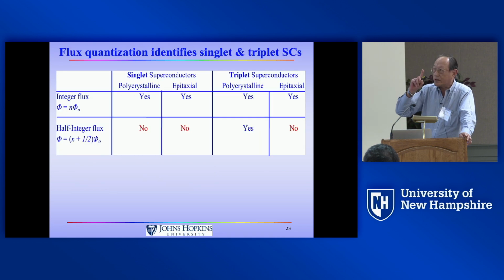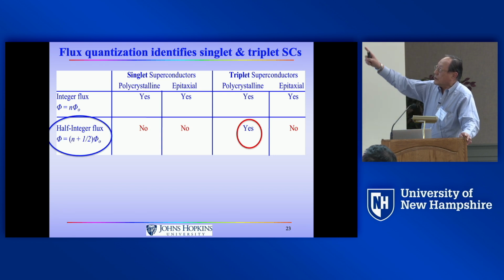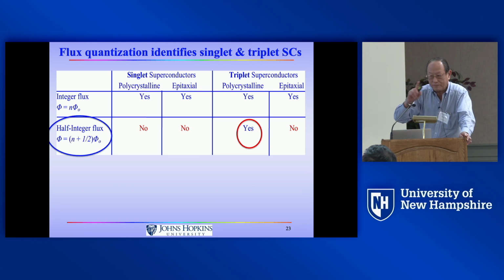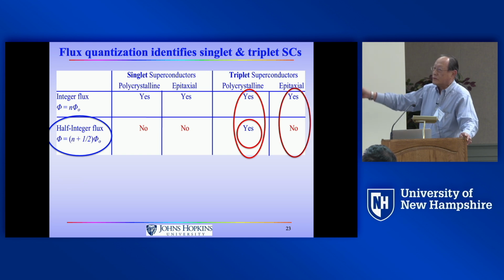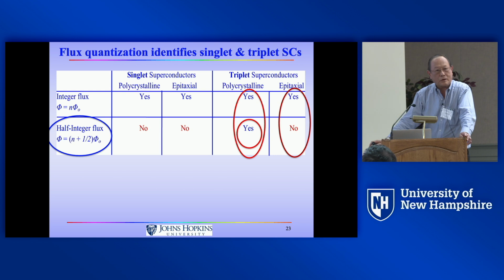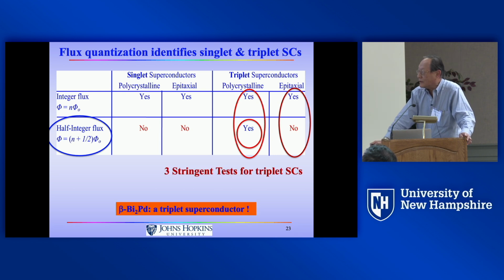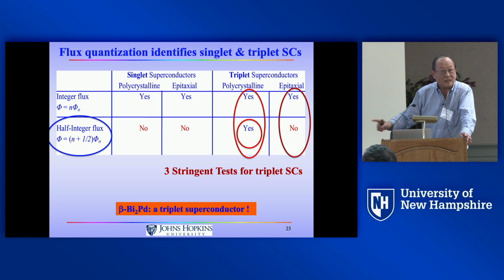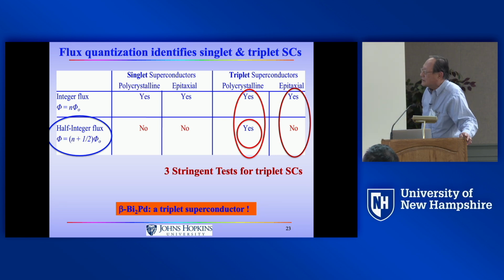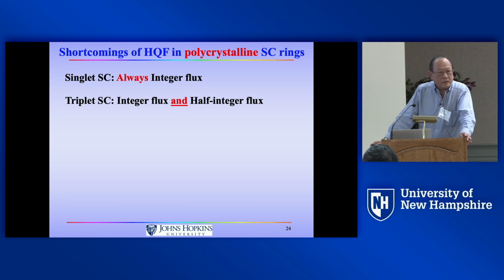So there are 3 criteria. If you have a singlet, forget it. You'll never see half flux under any circumstances. If it's a triplet, you will see half flux when you have polycrystalline some of the time. The other half of the time, you should see integer flux. When you have an epitaxial ring, you should see 0 half flux, all integers. It survived all 3. So I know, okay, at least I can tell my mother, I got a triplet, okay? It's good, but it's not good enough.